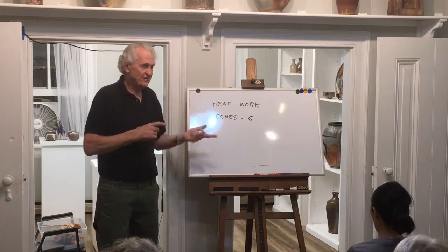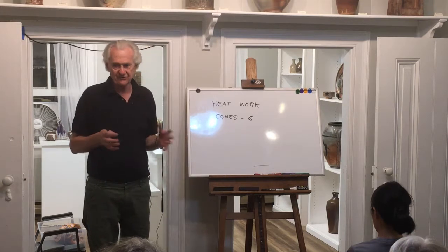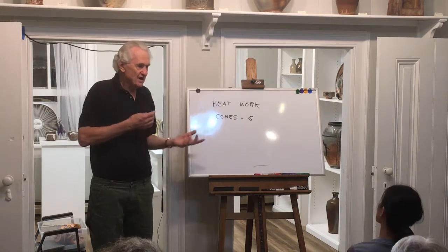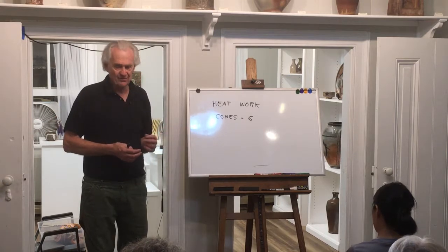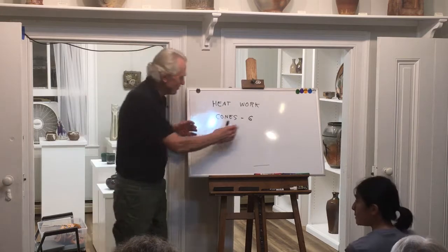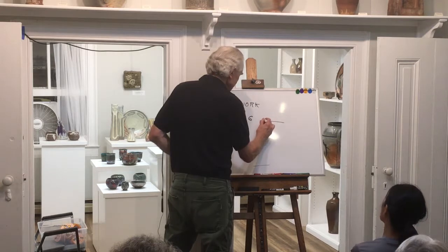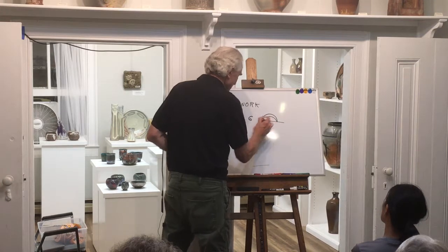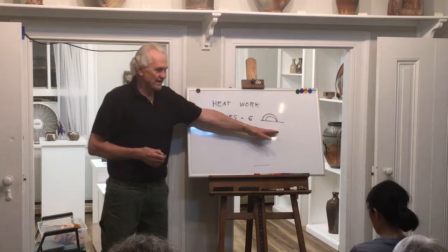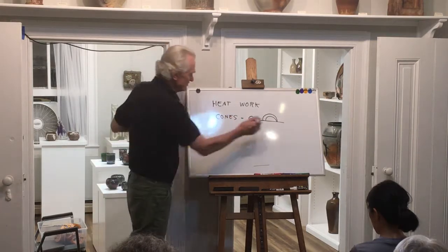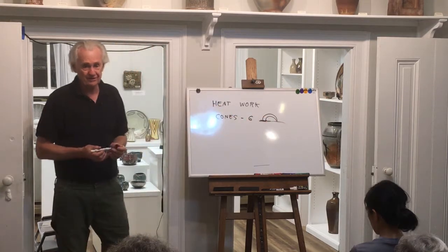I run into this a lot with teachers who are under pressure in schools or in institutions where they've got to crank a lot of pots through, and so they almost always do the fastest glaze firing they can do. And I've had people say, well, then, I did a perfect firing. I put cones in. The cone is just where. By the way, when a cone bends, you do it until just the tip touches. That's down. When it's lying like a limp amoeba or blob on the floor, that's overfired. So you fire it until the tip basically touches the same level as the base. That's done. Anything past that is overfired.